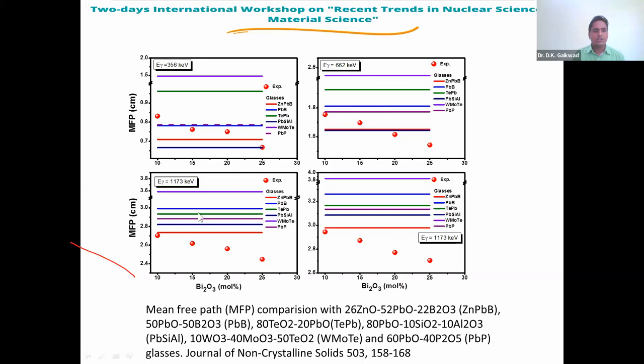Again, if we increase the energy, we can see the mean free path of all synthesized glasses is very low. Again, at very high energy, you can see the mean free path is very low compared to the other glasses. A low mean free path means high shielding capacity, right? So we saw that all lead and heavy metal oxide glasses have a higher mean free path than the synthesized glasses, and then we can say that the synthesized system has good shielding capacity compared to the other lead and zinc glasses.